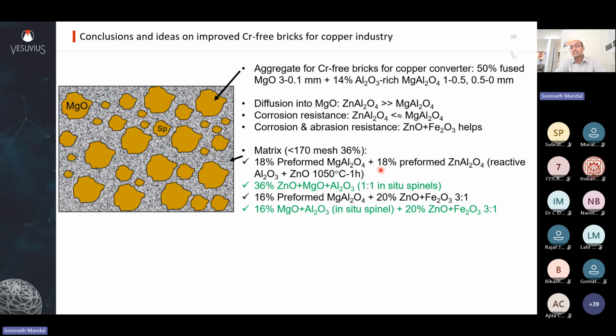An alternative and cheaper way would be to add the precursors in a 1:1:2 ratio, to form 1:1 in situ spinel of zinc aluminate and magnesium aluminate in the matrix. And then another idea would be to have 16% magnesium aluminate, and you have 20% doping of this 3:1 zinc and iron oxide. And then a variant of this can be, you can have in situ spinel.